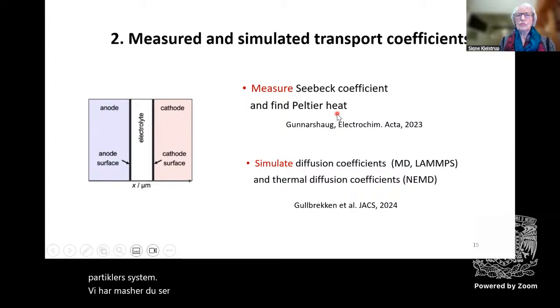And that is a pain, because there are so many coefficients, but we have now, we think, all of them for this particular system. We have measured the Seebeck coefficient to provide the Peltier heat. We have simulated diffusion coefficients and thermal diffusion coefficients using molecular dynamics simulations. So here is a measurement of the Seebeck coefficient.